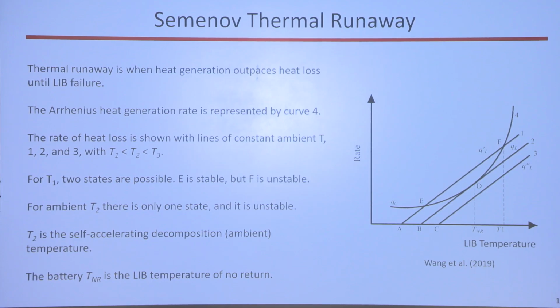So it turns out batteries, the heat release rate kind of has an Arrhenius type of behavior shown by that curve 4. So it looks like an exponential increase; sometimes as you double the temperature, you'll have 10 times the heat release rate. But basically the temperature of a battery follows that curve 4. Low temperatures, you have no heat release rate, but as the temperature goes up and up, you get an Arrhenius increase in heat release rate. So that's curve 4, the heat release rate inside the battery as a function of the battery's temperature.